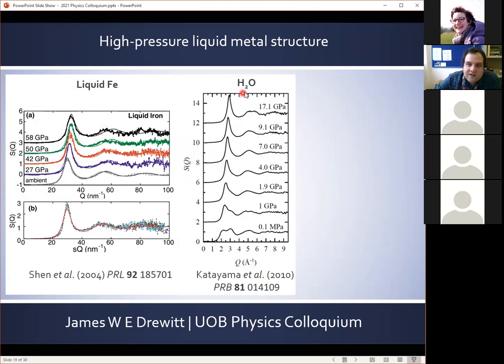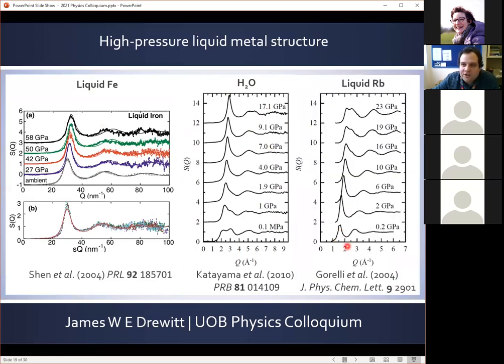But this isn't always the case. We see liquids can have a complex structure. Let's take water, for example, and at ambient conditions, water has this complex structure. But with increasing pressure, increasing densification, water undergoes a transformation and actually behaves more like an ideal, simple liquid at high pressures. But again, it isn't a given that liquids will transform to simple behavior at high pressures. For example, liquid rubidium has a simple liquid structure at low pressures, but undergoes a simple to complex liquid transformation at high pressures. And this is indicated by the splitting of this first peak in the structure factor. We see the development of a shoulder and a new peak, which we also see in our water structure factor, which disappears when it becomes a more simple liquid.